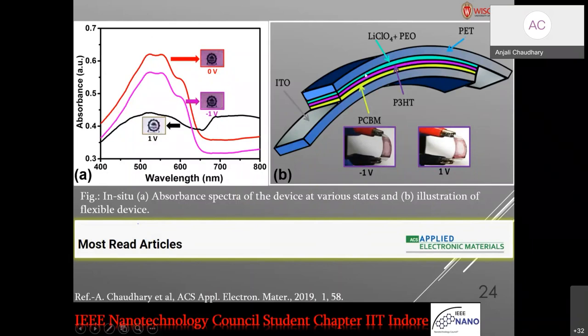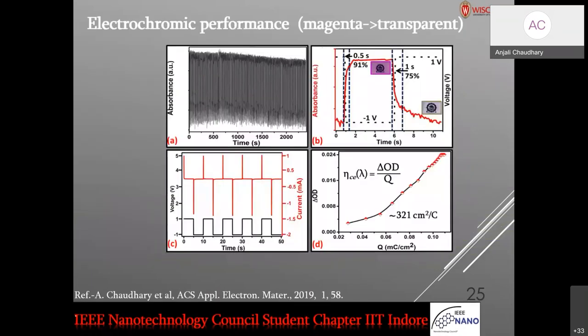And this is the flexible device that we have fabricated using this. This is just simply our demonstration of how we can make a flexible device. And to see how its performance is going on, we do UV-vis kinetics and then see how long it is stable in absorbance and what is the switching time it takes to switch between magenta and transparent state. And it takes 0.5 and 1 seconds to switch between its two transmission states.